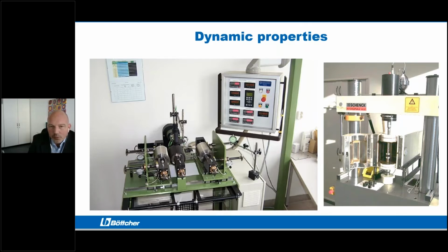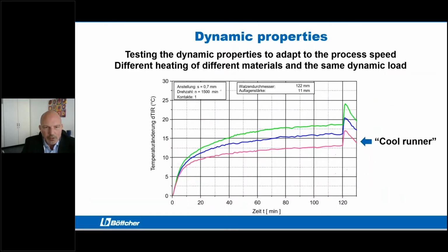We have also the possibility to do some dynamic tests, which means not only in theory, but we can also do real life tests with our elastomer compounds. And what is the reason behind? Because when we do these kinds of tests, we also can check the performance under production process requirements. This means, for example, how is the performance when you have some increase in pressure? Will the covering stay cool or will it heat up? So this is also one part which is important to have a reliable and optimized production process in your lamination or coating or other application.